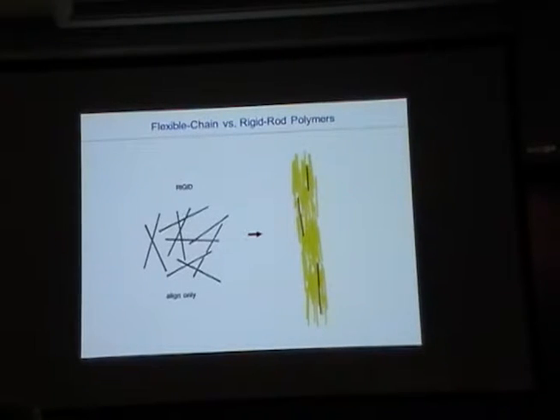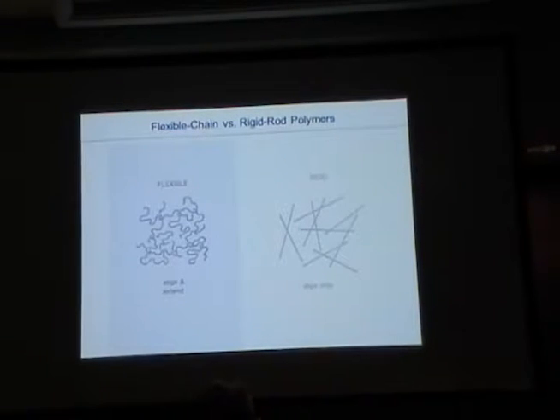The problem though is, and that depends on the molecular weight, you think it would be very easy to orient now these sticks. Just press them through a nozzle or whatever. However, once they dry, the molecules relax and you always end up with a misalignment. So therefore Kevlar is actually not as strong as polyethylene.